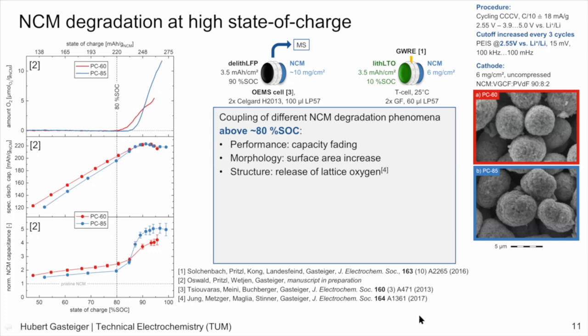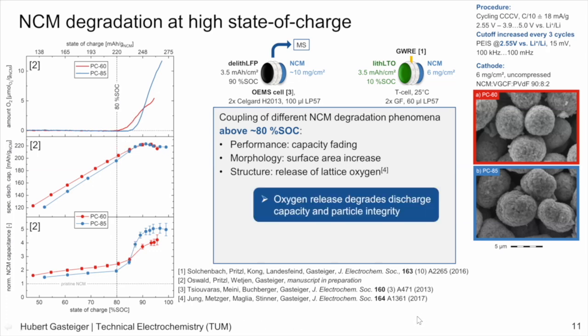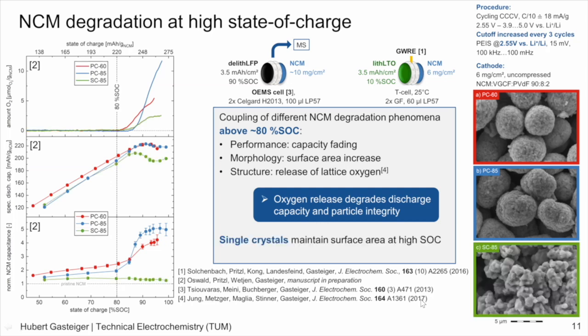these two materials. So the oxygen release leads to a cracking or enhanced cracking of the material and increases the surface area due to particle cracking. The other thing is when we use a single crystal material. These two materials have the same composition; the PC85 is polycrystalline, the SC85 is single crystalline. What we see there is that even when we go into oxygen evolution, we see no particle cracking, right?